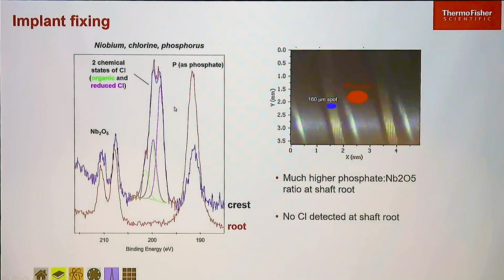If we look in the shaft and in the crest and root regions, in the crest we can see quite a lot of chlorine in two chemical states, both organic and reduced. So we've got some chloride present and some organic chlorine, possibly again left over from cleaning if it's been solvent cleaned and not been completely removed after that.